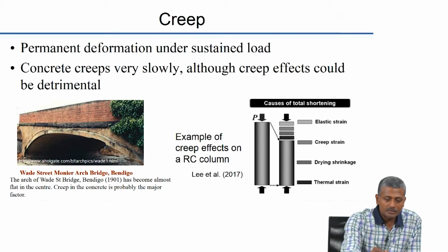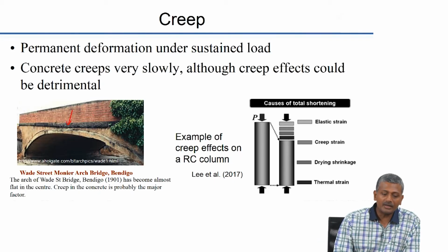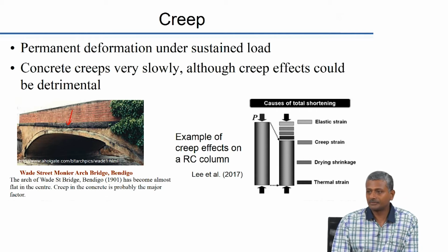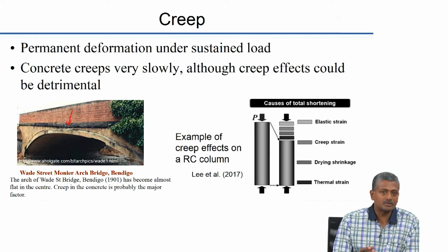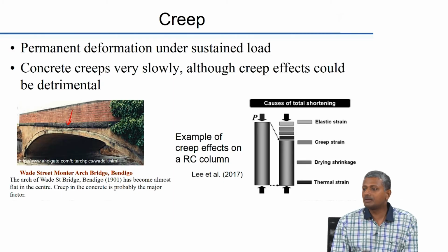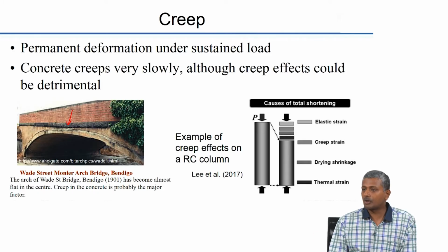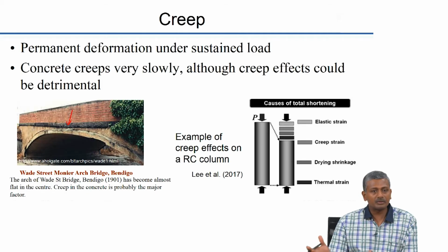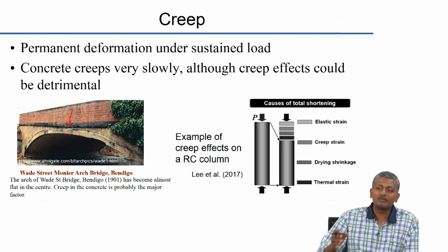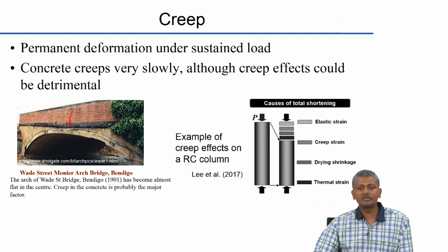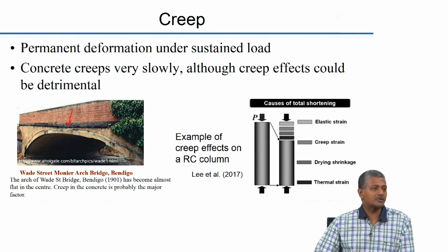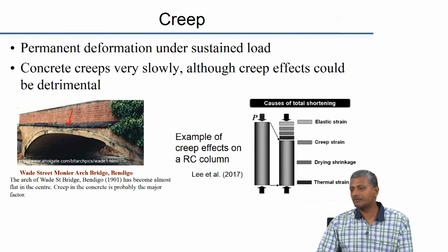So, you see here this sustained loading on this arch has completely flattened the top surface, and this has happened over many years. Obviously, this is not something that happens very quickly. Concrete, even at moderately high temperatures, 40 to 50 degrees Celsius, will have a very low rate of creep. Compare this to a polymer, the creep rate of a polymer is going to be extremely high. You see on an asphalt concrete pavement surface that when you get to summer, you start seeing the deformations under the wheel path. What do we call that as? The deformation under wheel path? Rutting, yeah, rutting. And that rutting is basically happening because of the very highly viscoelastic behavior of asphalt.